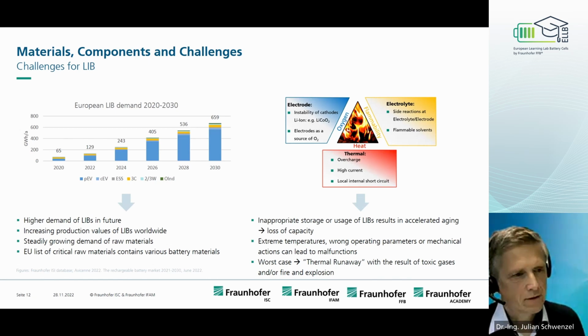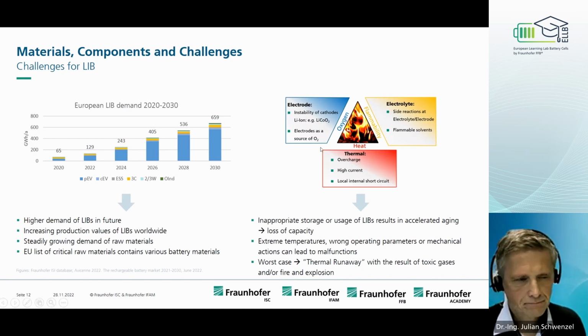And also about the safety. Inappropriate storage or usage of LIBs results in accelerated aging. So this means the loss of capacity. Extreme temperature, wrong operation parameters or mechanical action can also lead to malfunctions. And in the worst case, we call it thermal runaway, with the result of toxic gases and fire or explosion, which means this has to be controlled, maybe by using non-flammable electrolytes to control the heat and also to reduce the oxygen. And once you have oxygen from outside, from the atmosphere, or also from the materials like here from lithium cobalt oxide.